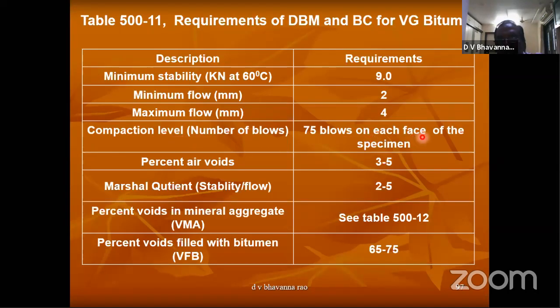Compaction level 75 blows on each side of the specimen. Percent air voids 3 to 5%. Marshall Quotient also 2 to 5%. Percent voids in mineral aggregates, the earlier table we have shown. Percent voids filled with bitumen 65 to 75, which means that the voids present in the mineral aggregate, that volume 65 to 75% we have to fill with bitumen. The balance remaining portion is called air voids. It is 3 to 5%.